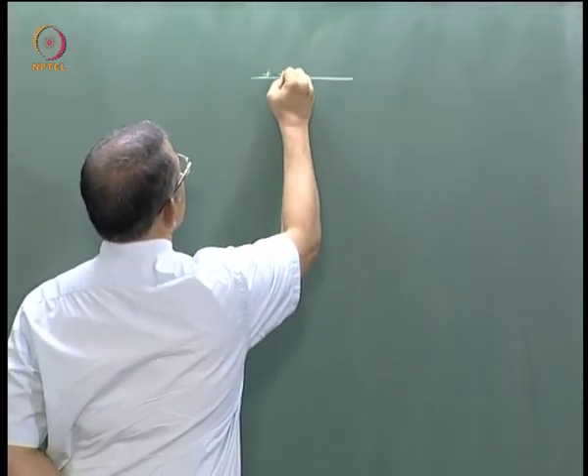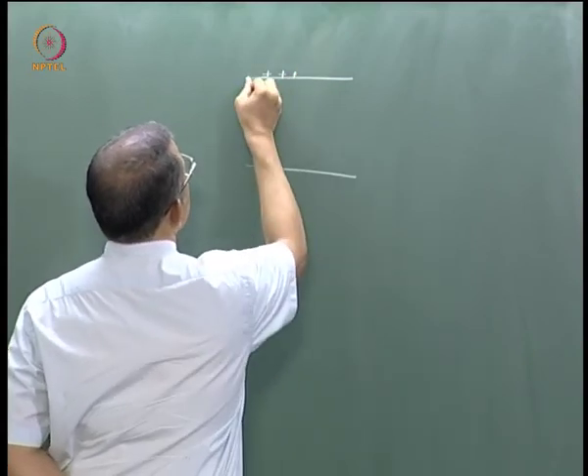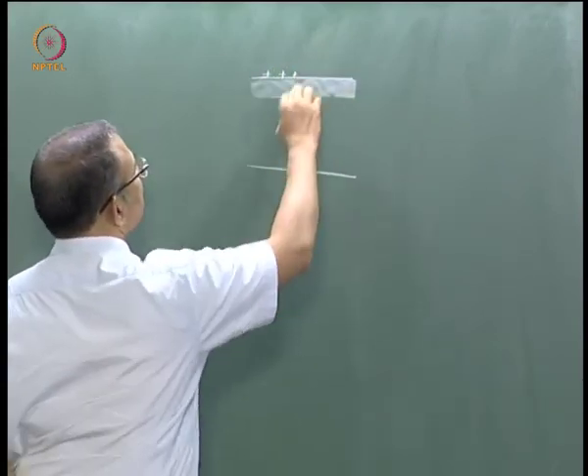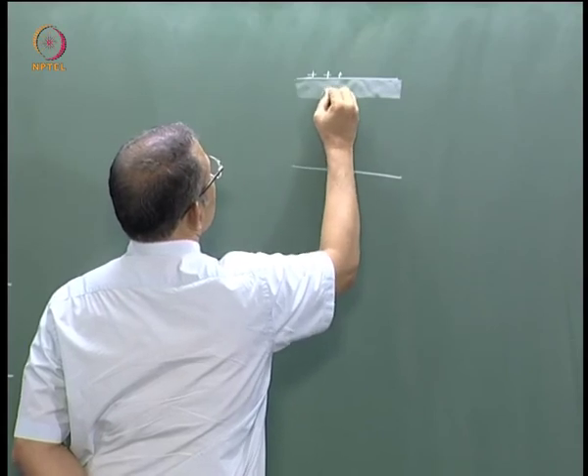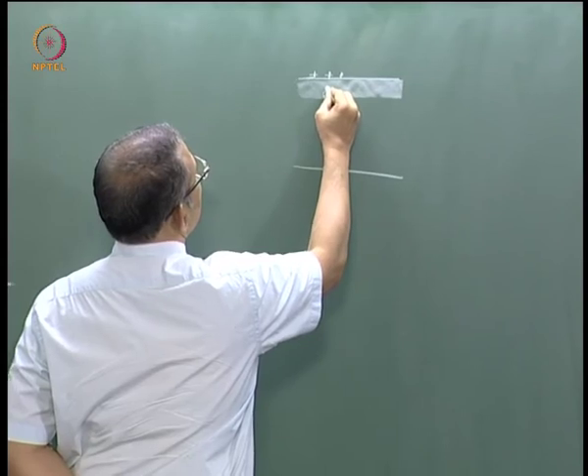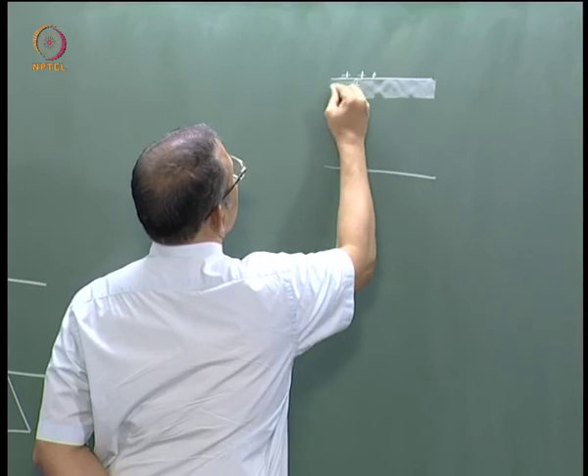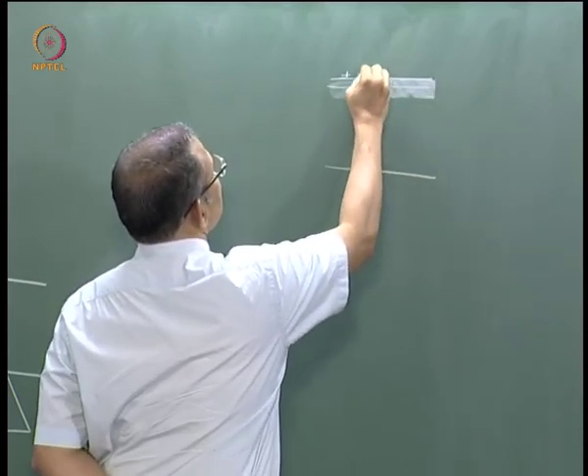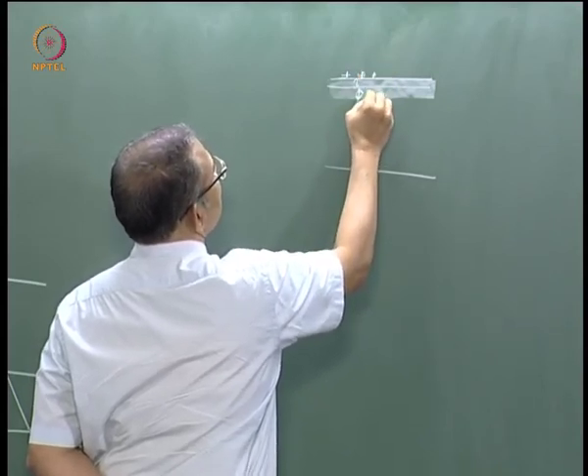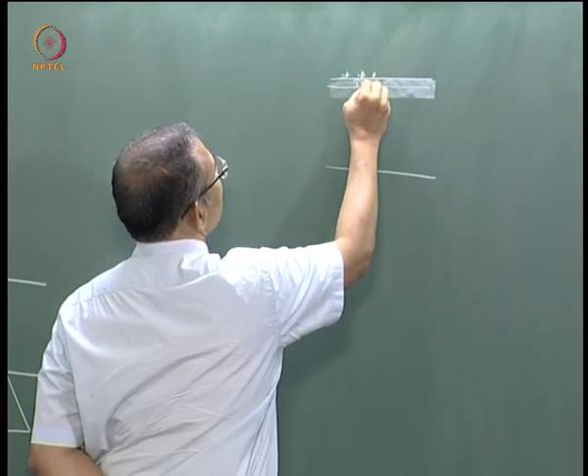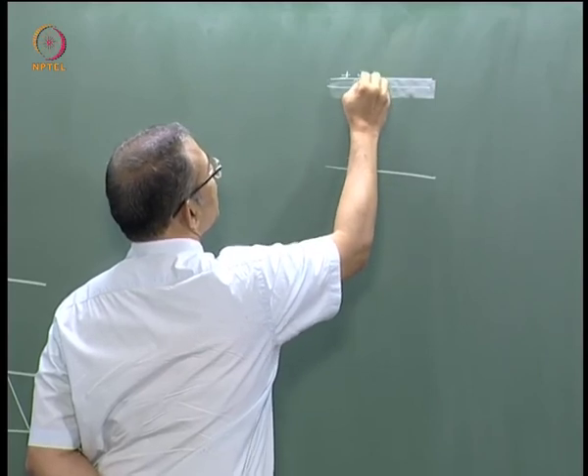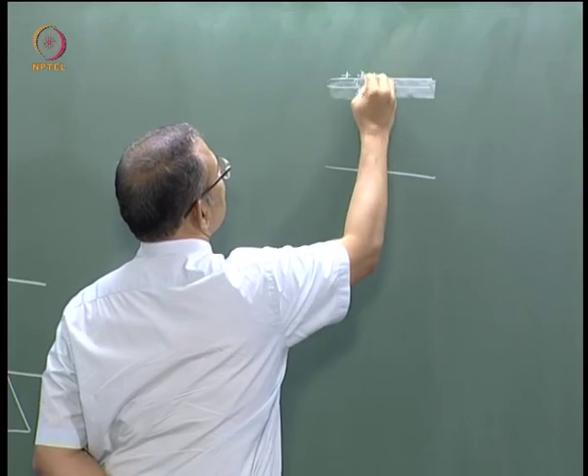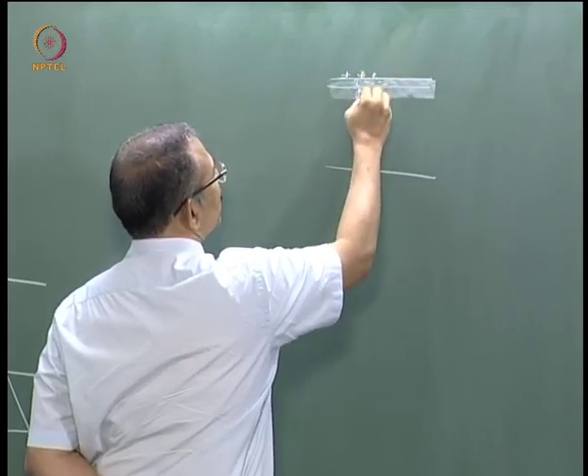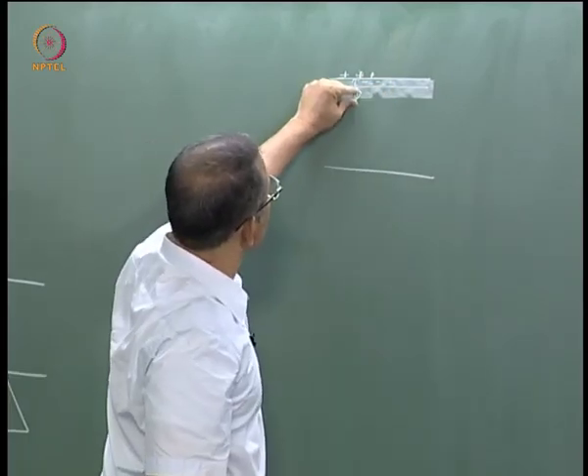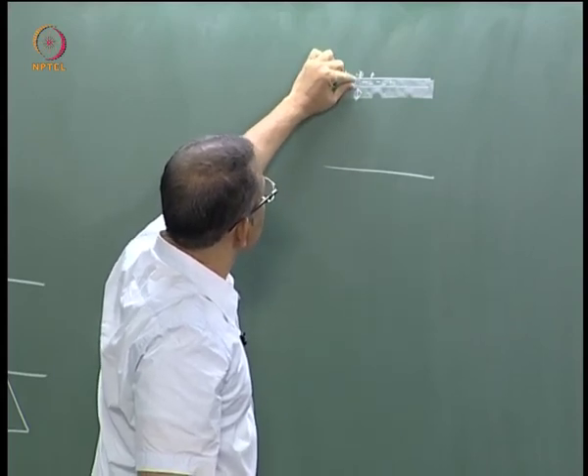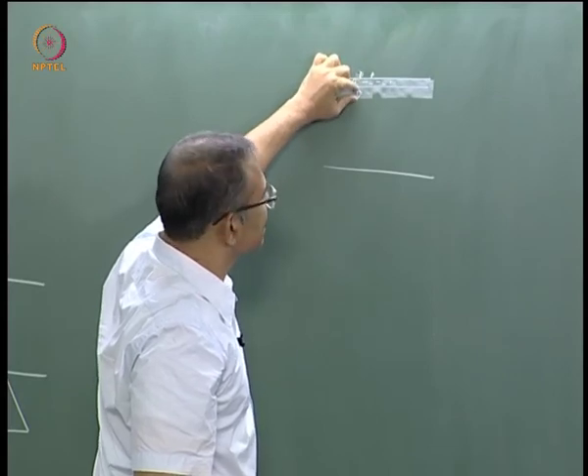So, these are the charges which may be present, let us say here, and this is the so called region of the mobile carriers near the surface. Now, in this region you can see that if I consider the mobile carriers in this region, these carriers are screened by the carriers above. So if I were to take the effect of this positive charge on the carriers here, that would be much less than the effect of this positive charge on these carriers, because these carriers will prevent this positive charge from having an effect on these carriers, right. They will terminate some of the field lines. Let us say if these are negatively charged electrons, then field line from the positive charge would terminate here, it would not come to this point, right. That is why these mobile carriers are said to be screened by mobile carriers above, and therefore the effect of these charges on the mobile carriers is less. So this is the so called screening effect.